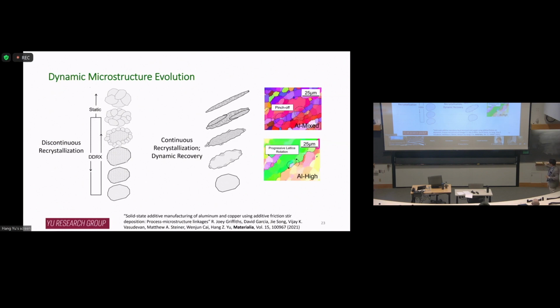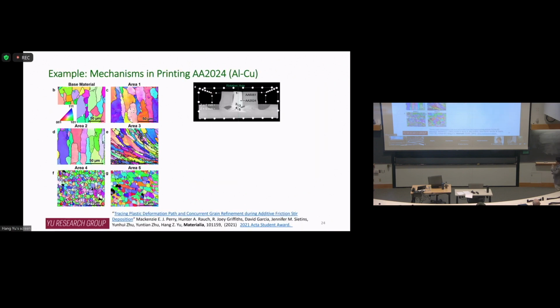Another possibility is commonly seen in materials with high stacking fault energy, in which case you have sufficient dynamic recovery. During deformation, you're going to have dislocation wall formation to form subgrain structures. Okay? And then as deformation proceeds, the misorientation angle between subgrains will increase more. They become high angle grain boundaries, giving continuous dynamic recrystallization. And if you remember, I just talked about these stop-action experiments. We try to freeze the shape of the tracer, but we can also freeze the microstructure, the grain structure, right? So if we do that, we can map the microstructure evolution along the flow path to figure out the mechanism better, right? And this is an example of 2024 aluminum, which is a copper-based aluminum alloy.